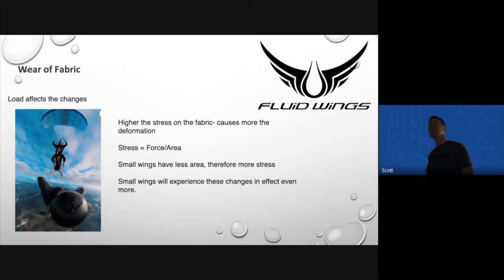But pound for pound, you've put more stress because you're putting a similar load over a smaller area. Stress is force over area, really conceptually, right? So if you're putting 200 pounds under a 60 square foot parachute, you're stressing that fabric in a unit stress at all the attachment points, at the top surface, at the bottom surface, you're stressing the fabric to a higher stress. You take that same 200-pound person and you put them under a 260, where the deflections matter less, it's also stress less. So it's not a function just of size and sensitivity. It's a function of the load you're putting under the wing, because we're not scaling the wing loadings accordingly. It may be a 0.5 on a 280. You're at a 3.0 maybe on a 60. So you've got to see that the wing loadings reflect a little bit of that stress that's distributed right across the wing.